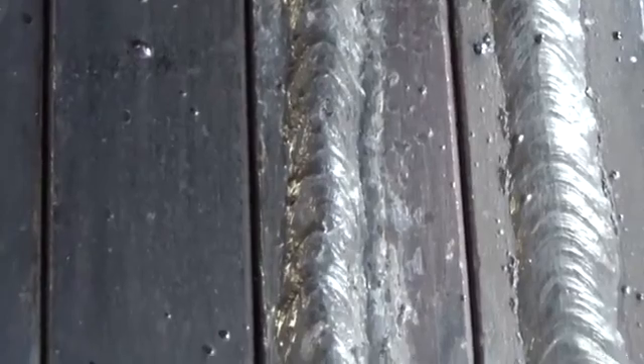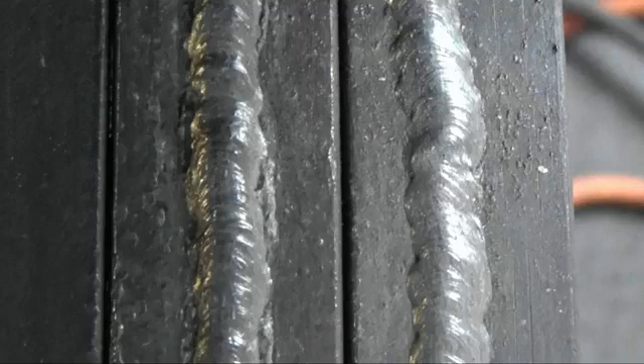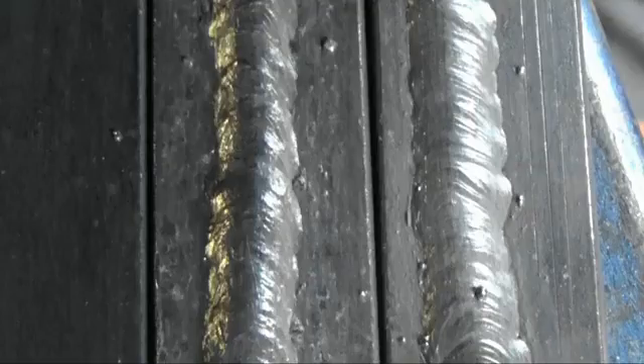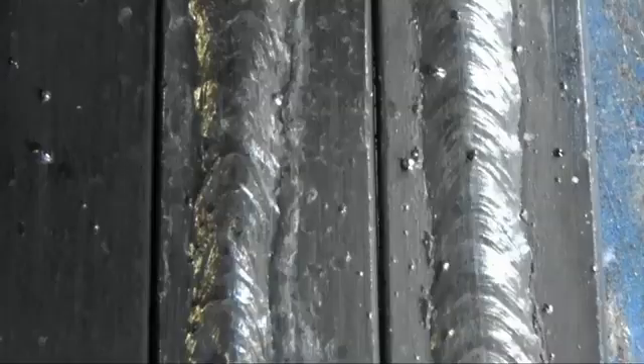Because of the high current value, the electrode has to move more quickly. It affects the weld uniformity, with narrow sections alternating with broader ones. The first figure: welds of insufficient currents. On the left, base-coated, on the right, rutile-coated electrode. The next figure: these seams are welded at average currents, 72 amperes on the left and 78 amperes on the right. Welding currents are close to optimal. The last figure: these seams are welded at the maximum allowable current for the electrodes. Definitely the current is too large.